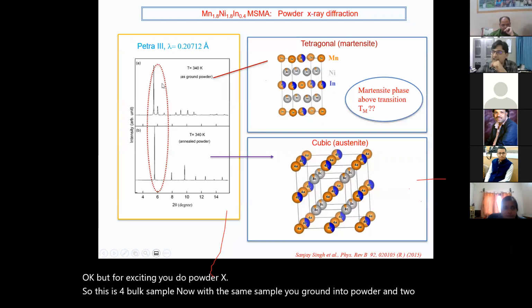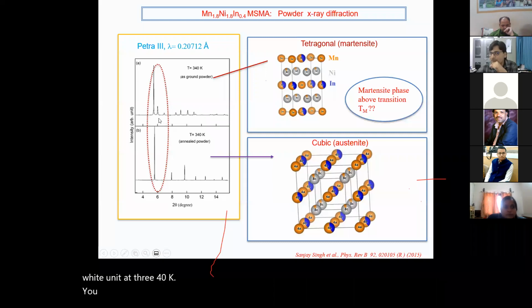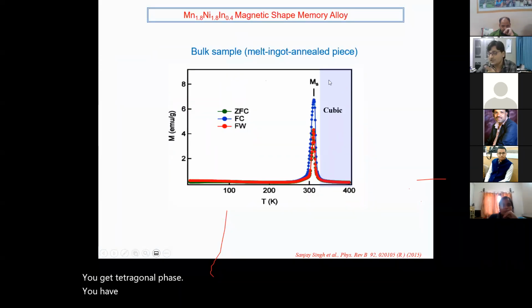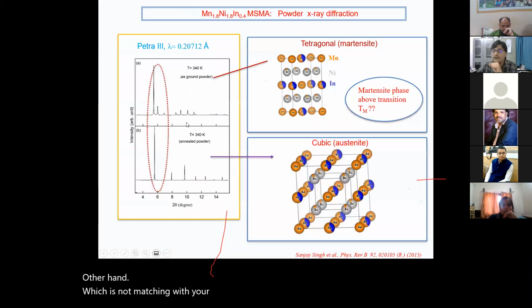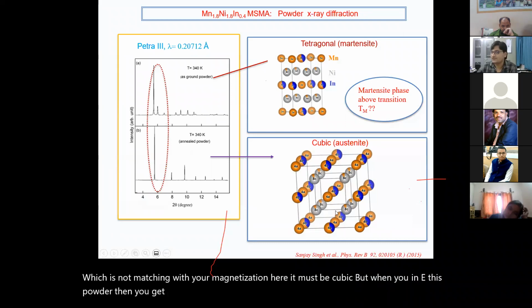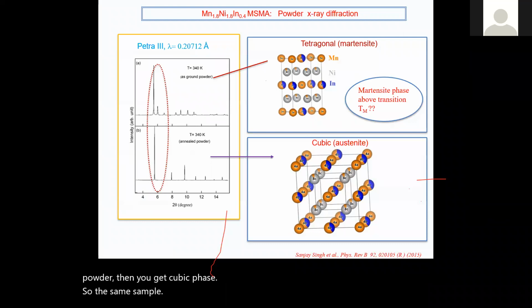At 340 K, you get the tetragonal phase. Here we have 3 peaks. After analysis you can know, but I'm just showing you, believe that you have the tetragonal phase. On the other hand, this does not match your magnetization. Here it must be cubic. But when you anneal this powder, then you get the cubic phase. So the same sample, powder XRD you did, it's tetragonal. When you anneal, it's cubic. So this is a puzzle.